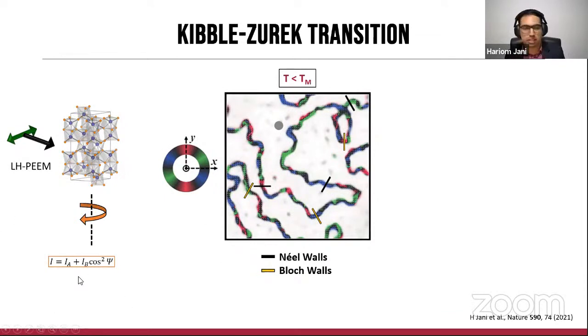Now, at the low temperature state, we can create a detailed in-plane vector map by using the angle-dependent experiment that I suggested earlier. And in the low temperature state, we're able to get these winding domain walls. It is clearly evident that we can see both Néel and Bloch textures, which suggests that these are not chiral objects, as expected, because there is no symmetry-breaking interaction in this terminal state.